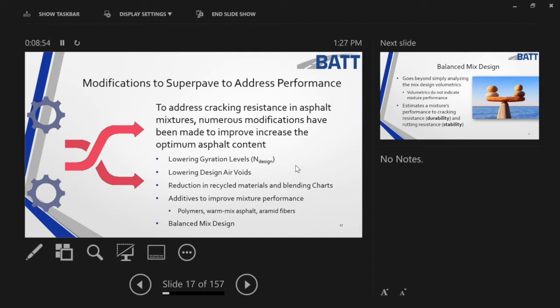Why was rutting important to solve? Rutting in a roadway causes this channel, as you know, and water pools in it, which causes hydroplaning, which can result in fatalities. We can live with cracks. We cannot live with rutting on a roadway. We can seal a crack. You can't seal a rut. You have to either mill or fill that rut.